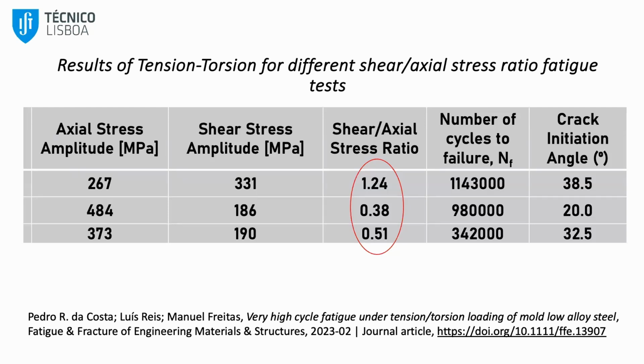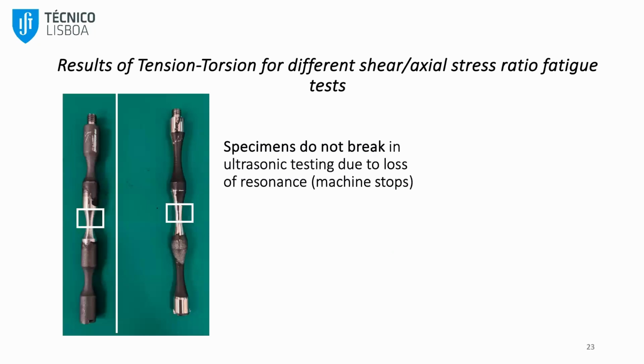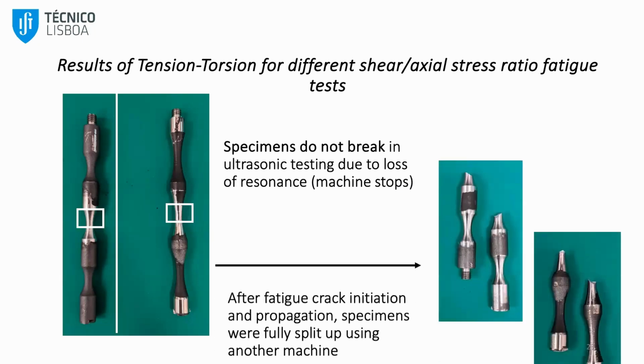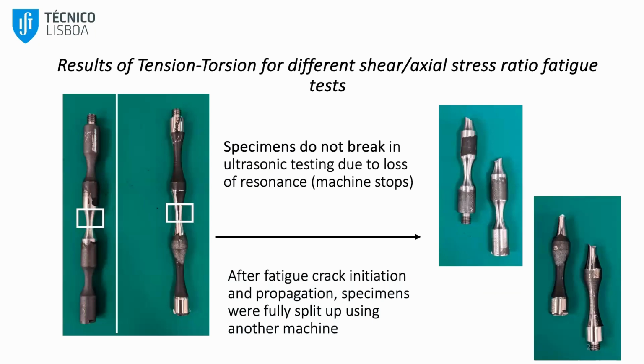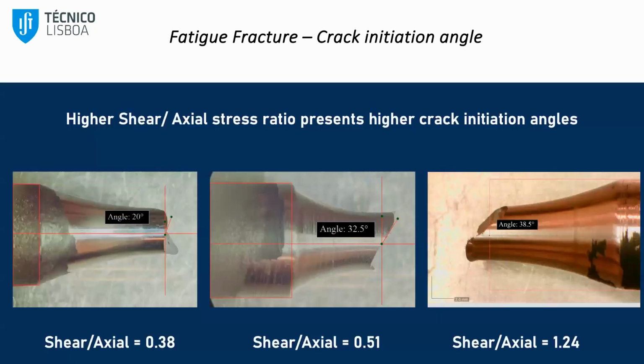So after that, we run the tests. This is an average for a set of specimens from each group. And we also measure the crack initiation angle at the end of the test. As you know, when you are performing this kind of tests, the specimen does not break, the machine stops because it loses resonance. And then we pick another machine just to fully split up the specimen. So we get this. And then after that, we have measured the crack initiation angle of each set of specimens.